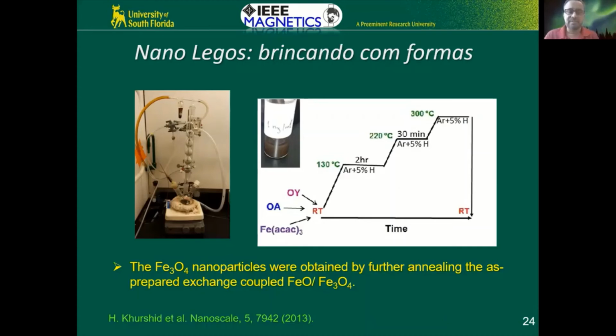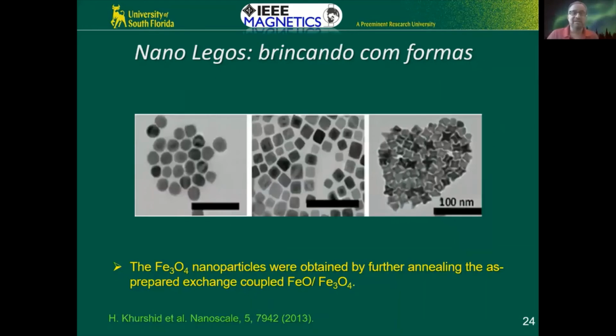So she said that I'm going to try to make core shell particles, FeO, Fe3O4, all oxide, no Kirkendall effect problem. At the same time, I'm going to change the shapes of these core shell particles. And I was like, okay, I'm not a chemist. So I said, good luck with that. And she went and came back with beautiful shape anisotropy. In other words, she came back with what I call nano Legos. Somehow she was able to play with the chemistry, and in the same system, she made spherical particles, she made cubes here, and she made these star-shaped particles.